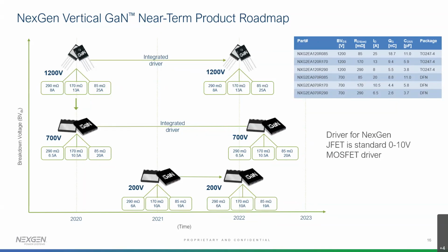As I said, we are starting out with a 1200 volt portfolio. But due to the fact that the breakdown voltage is mainly dependent on the thickness of the drift layer, immediately after the initial release of the 1200 volt versions, we can release the 700 volt version for a different set of applications. And that will then be followed in 2021 by a lower voltage version, 200 volt, as our current target. And in the 2022 region, we are planning to integrate drivers in the same package.